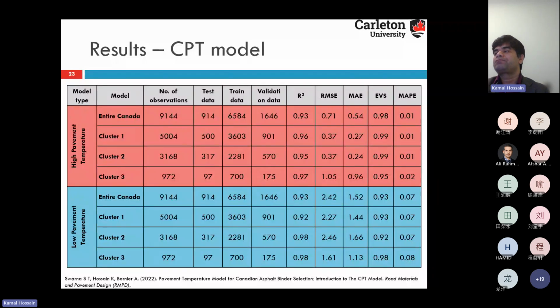So this graph shows the statistical validity of the models. The red section is the statistical result of the high pavement temperature prediction model, and the blue section is the statistical result of the low pavement temperature prediction model. The first panel is the entire Canada-wide model, and cluster 1, cluster 2 are the regional models. Just one indicator quickly: as you probably know, R-square is a good indicator of the prediction power of regression models. We got very high R-square values based on many observations and much testing and validating. So our R-square value is pretty high for all these models.